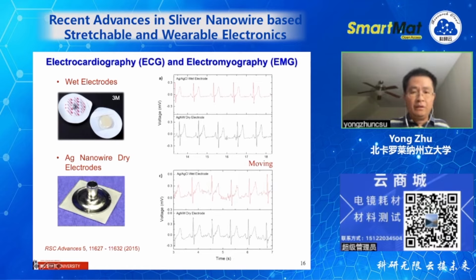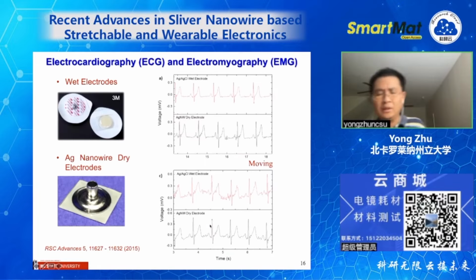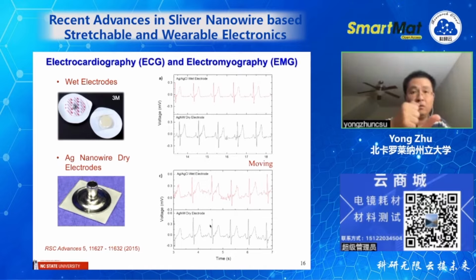This is our first work on this. Essentially, this is the wet commercial electrode, and this is our electrode, with very comparable signal. This is when the subject was sitting. When the subject was moving, the so-called motion artifacts are quite a problem for electrodes, because the electrode moves relative to the skin, causing noise. In that case, ours actually outperforms it, because we have a more stable interface.